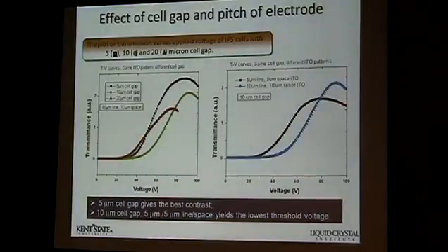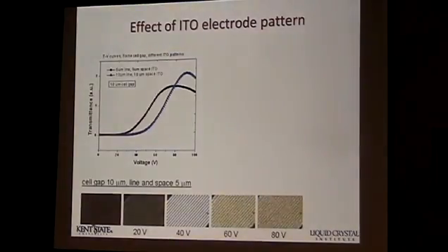It's roughly much lower in terms of the threshold. You see threshold here about 30 volts, and then the threshold here roughly around 50 volts. But turn on time also reduced. So I think optimizing this is important. So we have this electrode effect, and then I compare that.